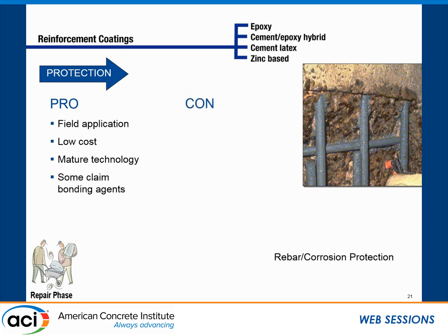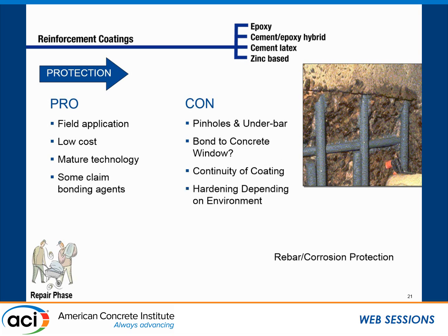The downside of reinforcement coatings: how do I get them underneath the steel? It's real hard to reach there. What about pinholes? What's their bond to concrete window? The longest I know of a bonding agent lasting is maybe 24 hours. The studies I've seen on our products and other people's, you start out pretty good, the longer you leave it open the worse it gets, and after 24 hours, not so good. There's also continuity of the coating. And their rate of hardening depends on the environment. Their chemical reactions are hydration reactions for setting up, so in cold conditions, they don't work so well.